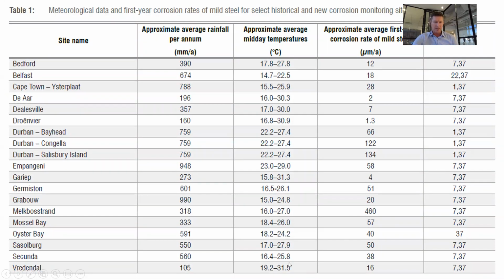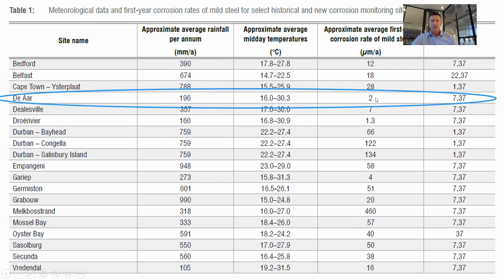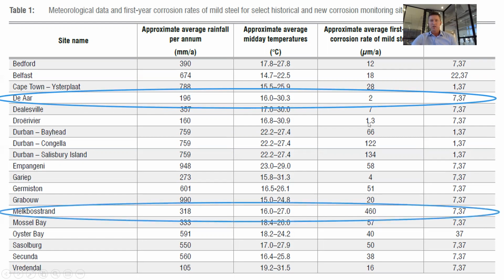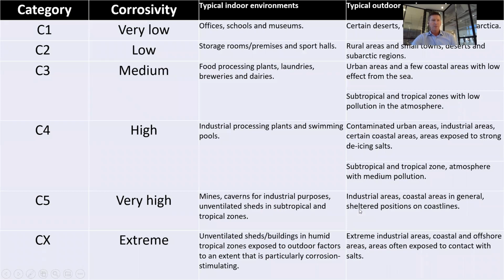Here's an example of an actual site that was recorded in the study. You'll see Melkbos Strand down here in the Western Cape recorded nearly 0.5 millimeter of corrosion on the West Coast in 1 year. In De Aar, on the other hand, recorded only 2 microns per annum. And here we see Melkbos Strand nearly 0.5 millimeter, 460 microns per year.